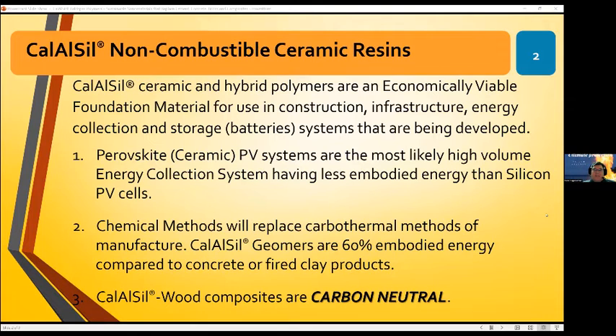So CalAlSil silicate resins, the first silicate hydrogels, which is the beginning of the process to create a silicate resin, is extremely high in thermal insulation or thermal mass. And that's essentially just due to the fact that up to 50%, somewhere between 44 and 50% of the material is water. So this is reasonably unique in the sense that there's not too many gels or hydrogels in the marketplace that are made from a ceramic that don't burn, that don't even char in a fire event, that is available to be deployed in an outback region or a desert style region.